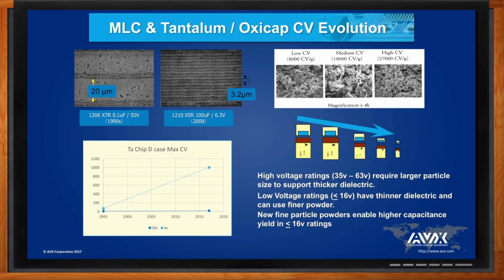Now, if you go back the other way and look at the high voltage ratings, you still need coarse grain powders for the higher voltage ratings, because the dielectric, you can't grow that thicker than the grain. So there's a limitation there. So if you look at this chart at the bottom left, what you're left with is, over the past 25 years, we've gone from 6.8 to 22 microfarads at a 50 volt rating, whereas we've gone from 68 to 1,000 microfarads at a 4 volt rating. So you can see the low voltage increase in capacitance is really significant for both of these technologies. And these have maintained lockstep with Moore's law, enabling the new generations of core caps.